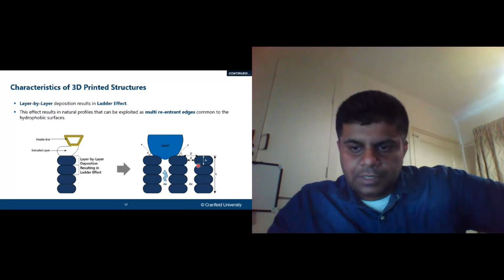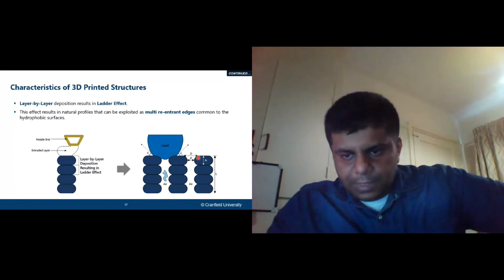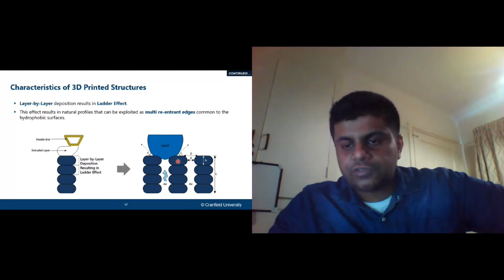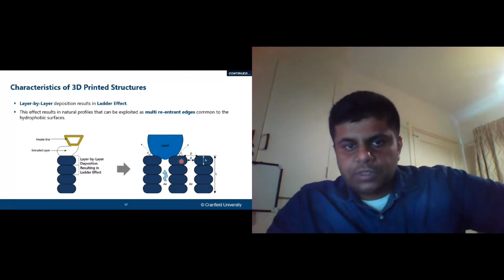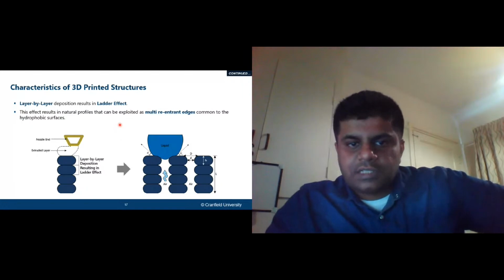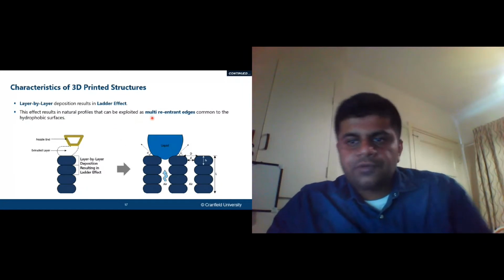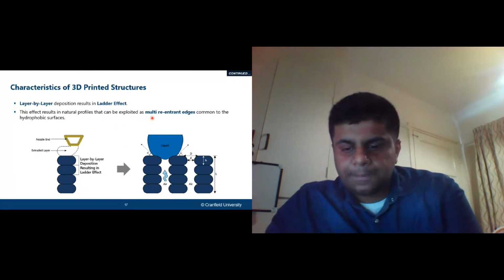In this particular experiment, we are modifying H, the layer height, and we are trying to study its effect. Our interest is not on the entire deposition structure, but only on the semicircular edges that you see over here. So basically, by modifying the layer height, we are changing the behavior that can be seen in these semicircular edges on your left and over here. This is the actual air entrapment side. The rest of the material is just for structural strength. I'm not going to discuss much on that. So this effect results in natural profiles that can be exploited as multi-reentrant edges common to hydrophobic surfaces.